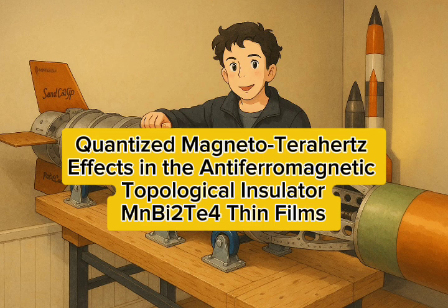And what were the Faraday rotation values there? Close to the theoretical quantized value? Remarkably close. At 0.4 terahertz, it reached about 3.1 milliradians at 5 Tesla and maybe 3.2 at 6 Tesla. The theoretical prediction for quantization in this limit is around 3.5 milliradians. Wow, that is close. So very suggestive of a quantized effect.